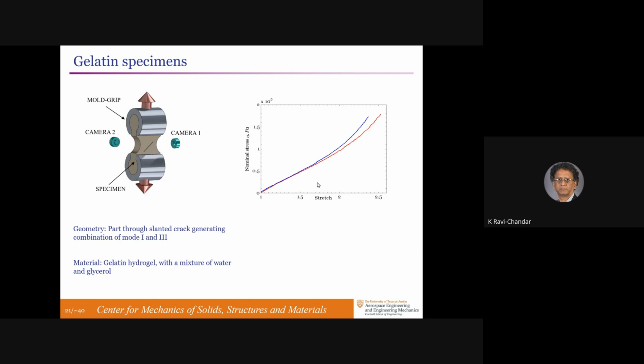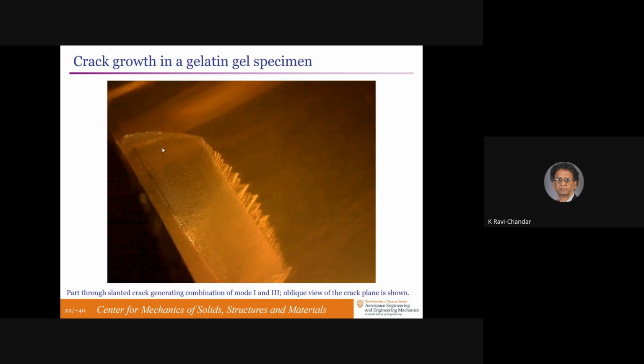Finally, how do they link up and grow? So for this, we have to create another experiment. This was done on a hydrogel, gelatin-based, the dessert that you make. So we made specimens out of gelatin and put them in mixed mode loading by pulling it in uniaxial tension, but put a sharp angled part-through crack at an angle, and observe what happens to that. This material is fairly linear in its elastic behavior up to very high stretch levels, but it's failing at fairly low stretch levels over most of its domain.